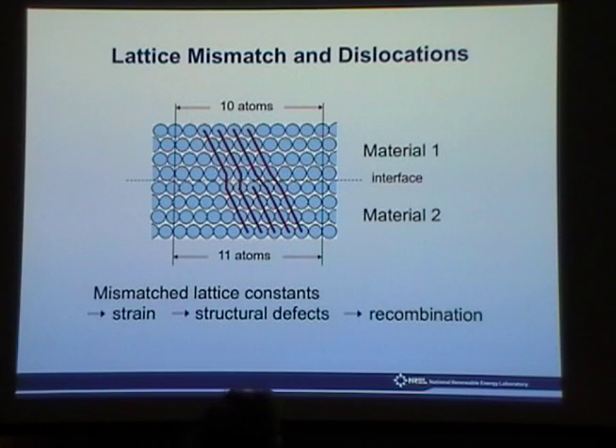In this case, that would mean that material 1 is being stretched, right? So that forces the crystal to store some strain energy. And that can happen for a few monolayers, maybe even for tens of nanometers, but it can only happen for so long before the crystal collapses and relaxes to its strain-free position. When it relaxes, that relaxation is mediated by the creation of dislocations.